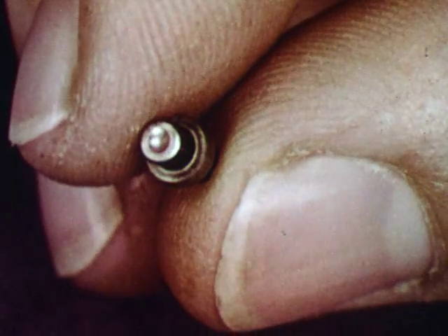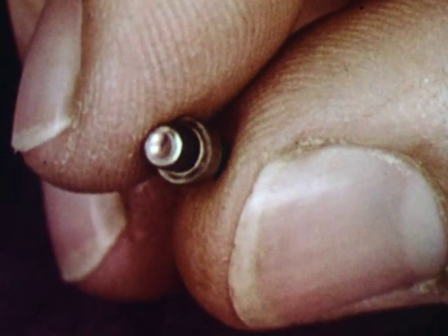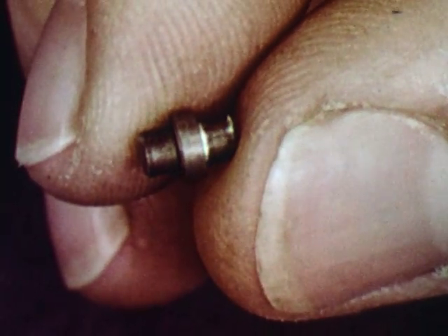This chainsaw rivet pin is made from 52100 steel wire at 225 per minute. The die is carbide and heading tools are high-speed steel. The pin is held to extreme tolerances. Collar diameter plus or minus 5/10,000ths of an inch. Shank plus or minus 1,000. Cold forming this part has saved 47% in material alone. The machine has a solid cutter and knockouts in the cone and finish punches.